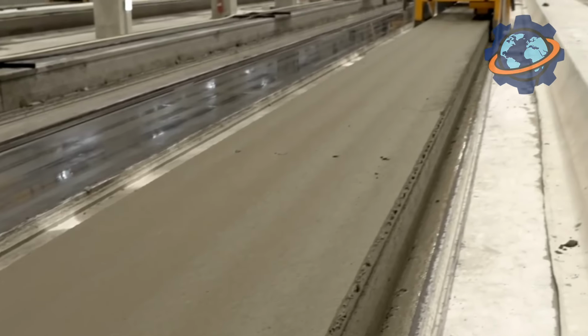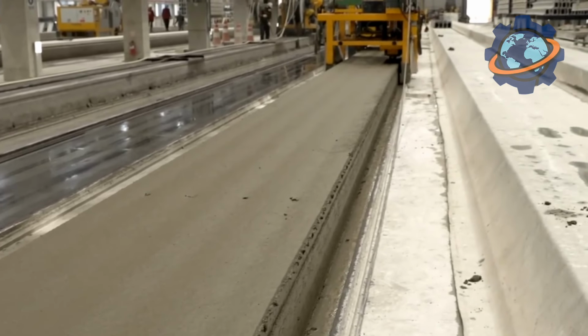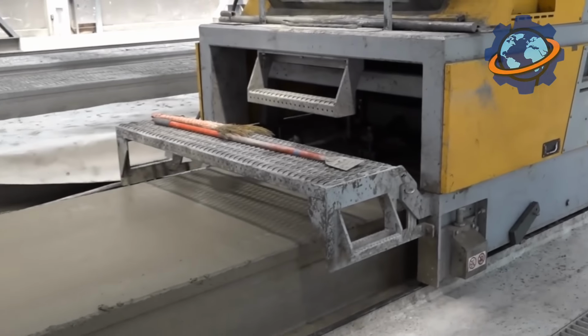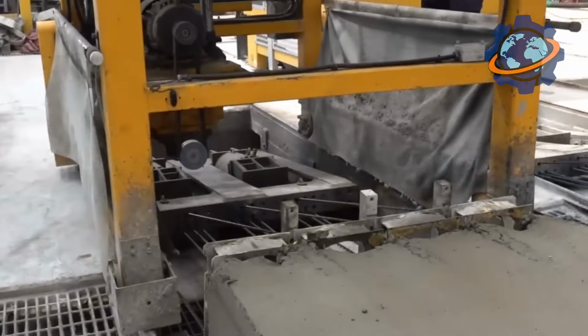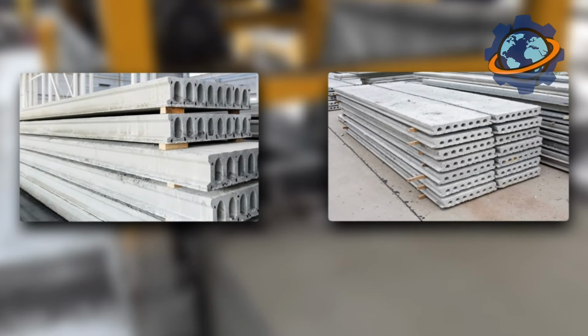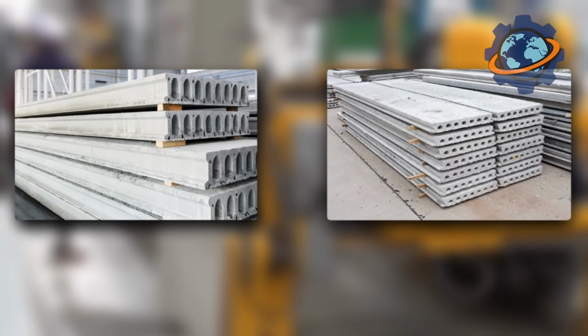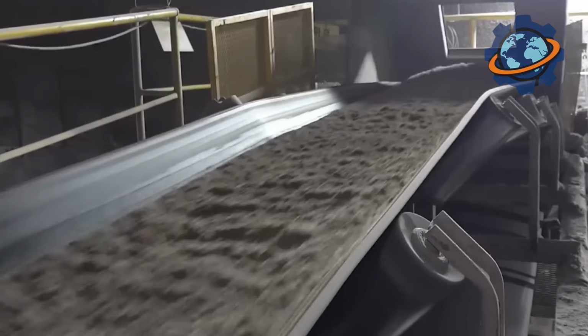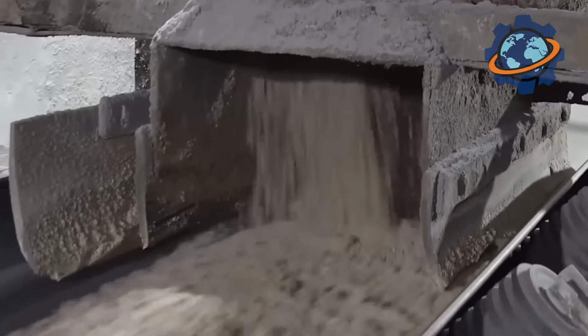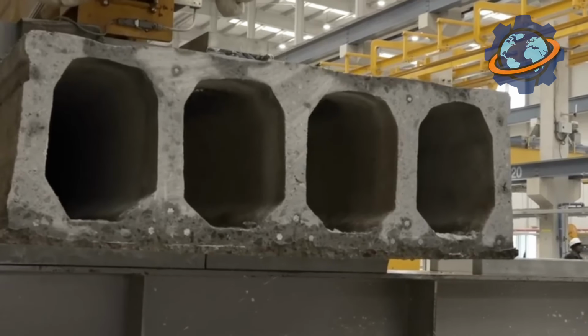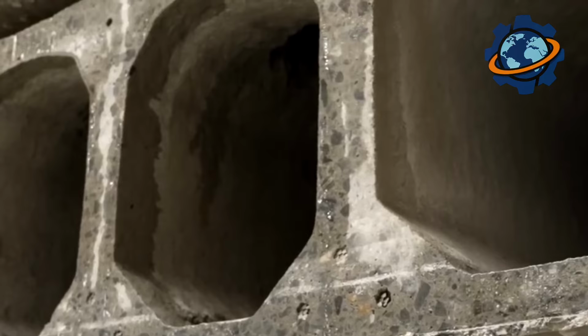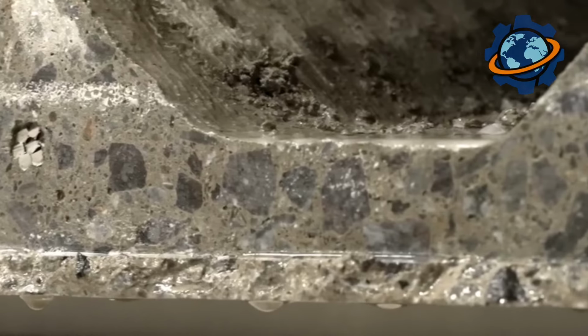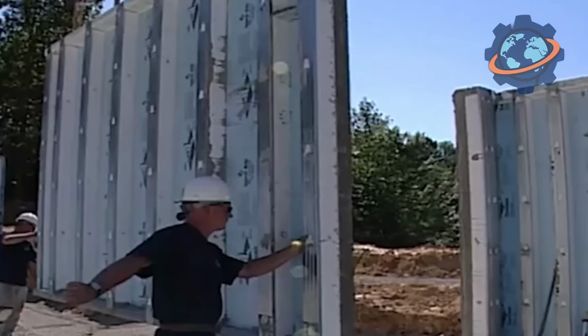The machine, like a giant concrete snail, slowly crawls forward, leaving in its wake a perfectly formed, endless concrete slab, with hollow cores inside and tensioned steel muscles hidden within its body. Because the concrete is so dry, it holds its shape instantly and doesn't sag. This is secret number 2. The voids, which make the slab 50% lighter than a solid one while barely reducing its strength, as the top and bottom sections do most of the work.